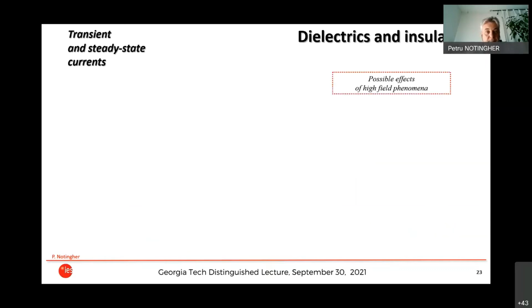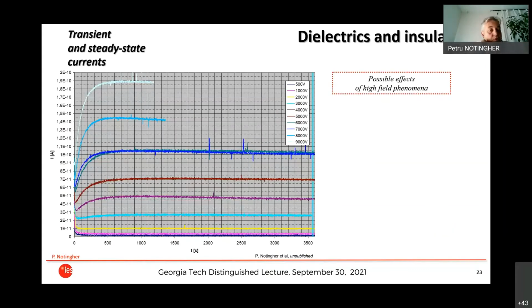I was talking about the memory of the material. Why should you do that? Because in fact, if you increase the field, you may have, and you will certainly have, the surprise to see that the material does not behave linearly above a certain field. So this is an example of a sample on which we have measured discharge currents. You see that here the current has almost the same shape for the low voltages, for the low field, and is almost proportional to the voltage.